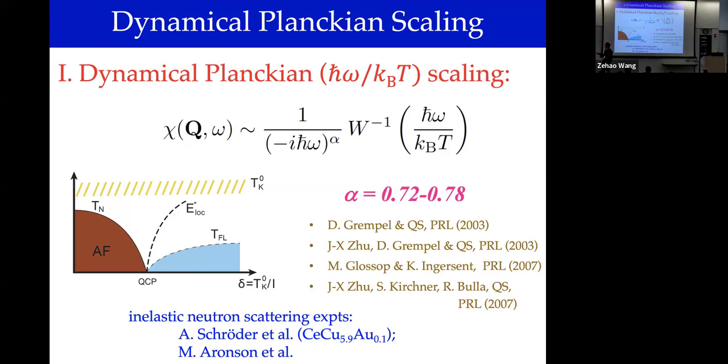Omega over T scaling means that the only energy scale at the quantum critical point at a finite temperature is k_B T. That means dimensional analysis works, and that's the signature of an unusual fixed point. In many ways, we are looking for the fixed point. If I had delved into the details of the calculations, I would have shown you that this critical point corresponds to a new fixed point that's entirely different from the Fermi liquid fixed point.